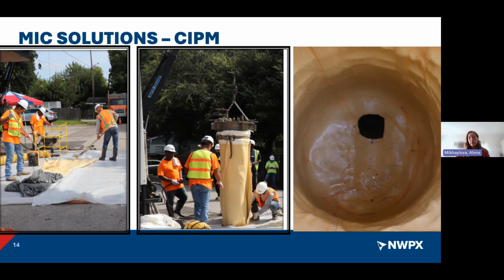So again, the benefit is, yes, it's very good for I&I. Some of the cons: it's more difficult to conform to complex shapes, like if you have some benches or troughs that you need to line. You would also need a bypass for this solution, unless you're not rehabilitating the bench and trough area, then you don't necessarily need a bypass. And again, it still relies on chemical adhesion, so preparation of the surface is paramount to make sure you have good adhesion. Most of the time it fails because it doesn't have good adhesion.